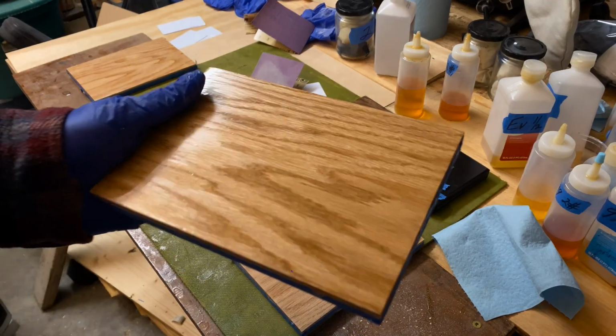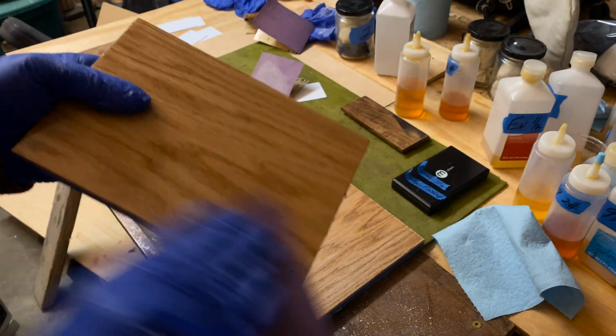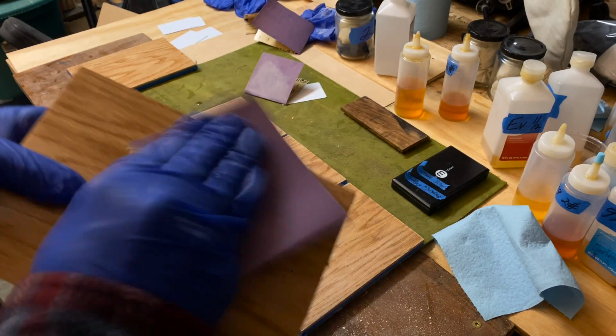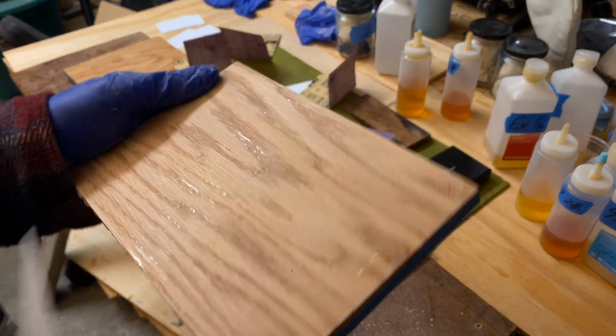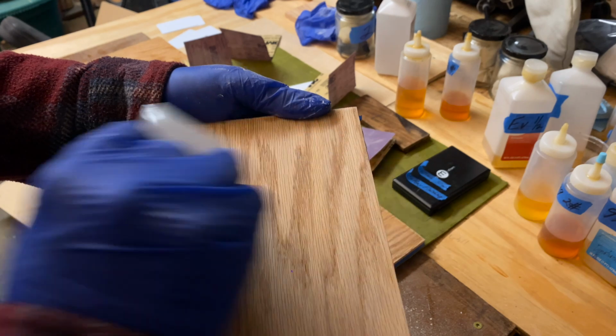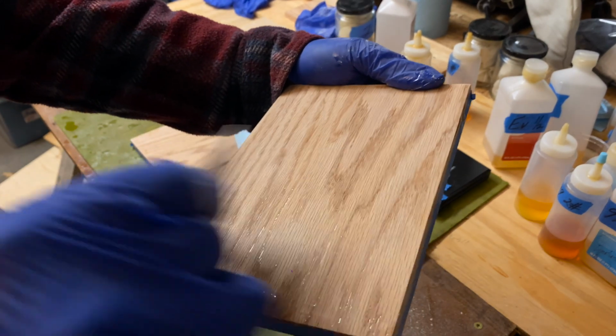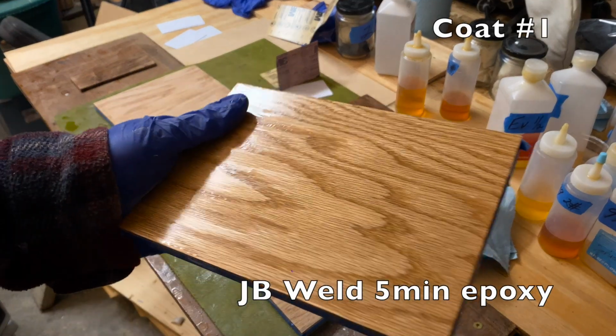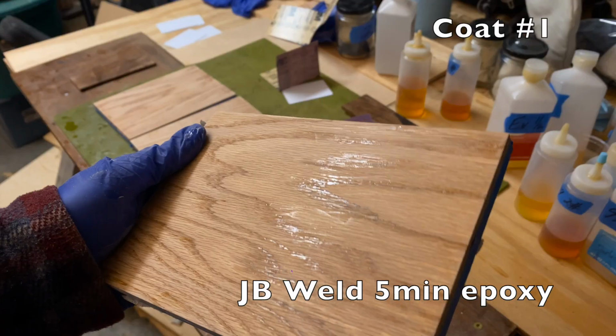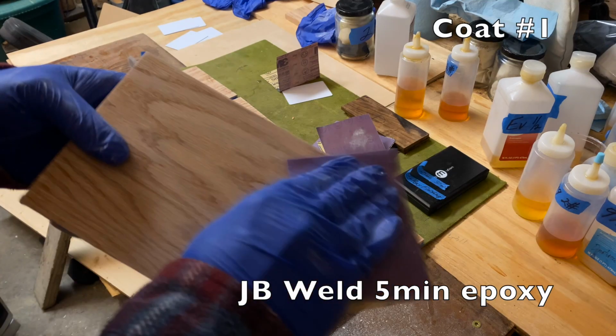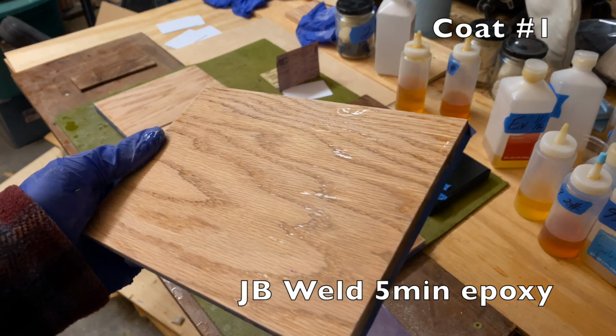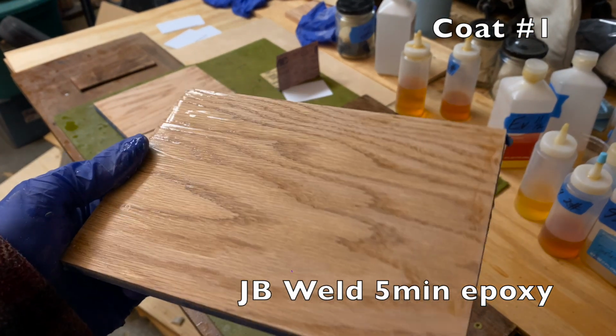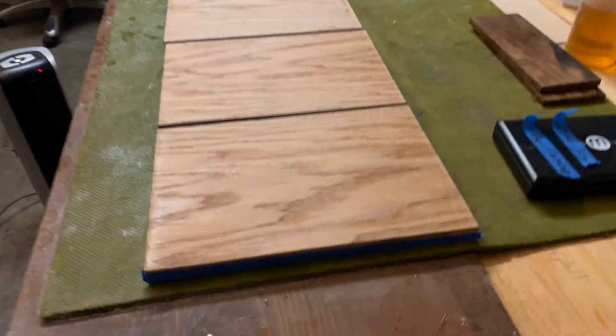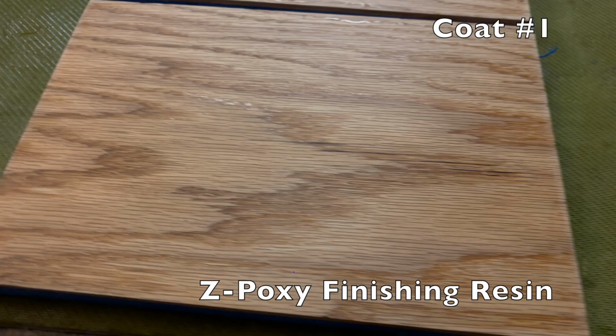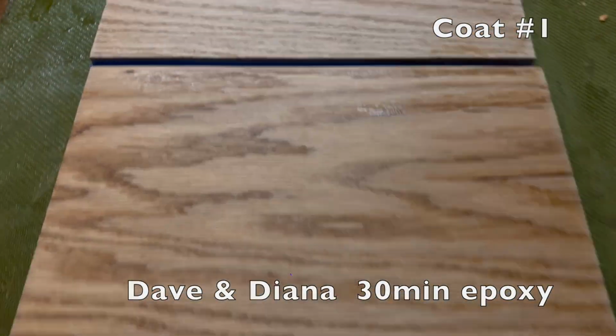For the Gorilla Clear epoxy, I went straight to the 220 grit, and it still took a little extra effort, but again, with an orbital sander, it would have been fine. And to me, it sounds like these last couple of boards with the thicker epoxies sound a little more filled than the first two boards that we tested at this point. With the JB Weld Clear-Weld, I started with a 320 grit, which proved to be a bit too fine, so it didn't take long to switch to the 220 grit, and it responded almost exactly like the Gorilla epoxy did with the 220. And here's a look at all the pieces sanded to 320 and ready for the next coat. It's interesting that it's hard to tell which side was sealed with shellac at this point.